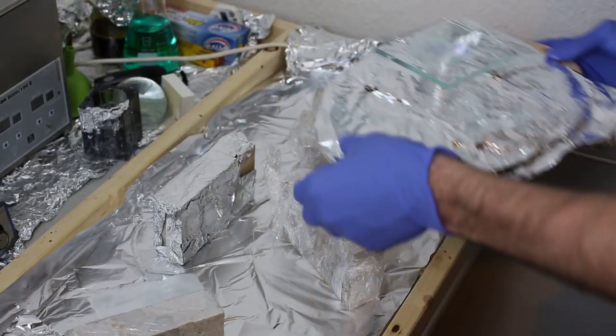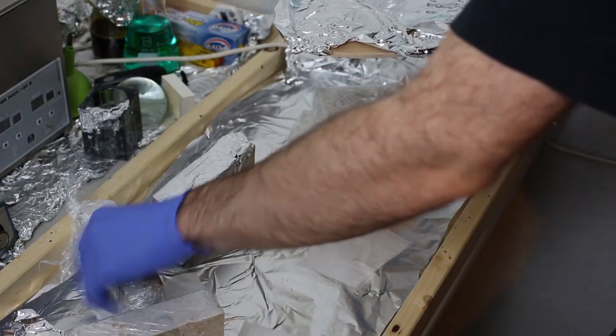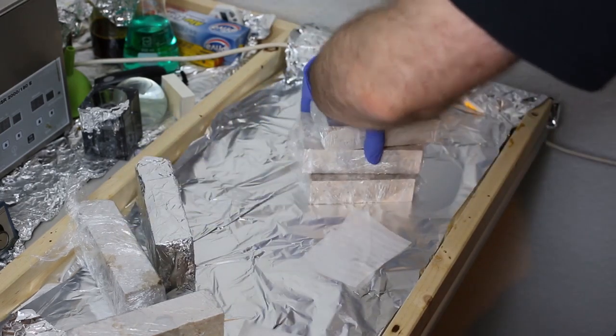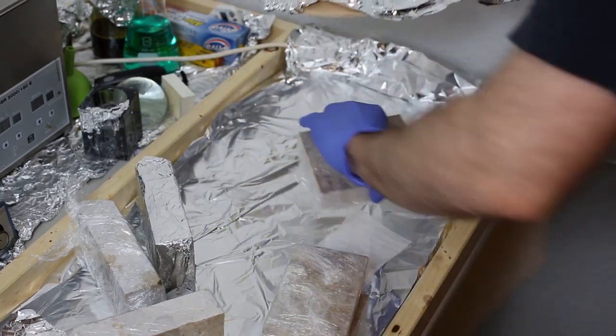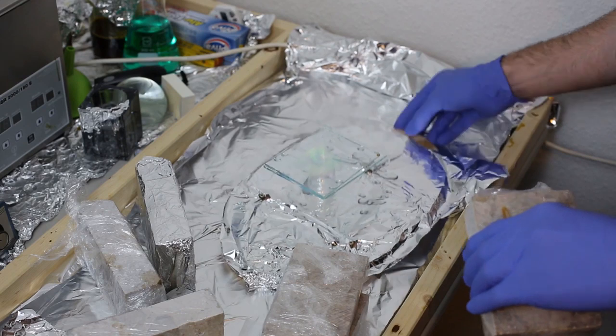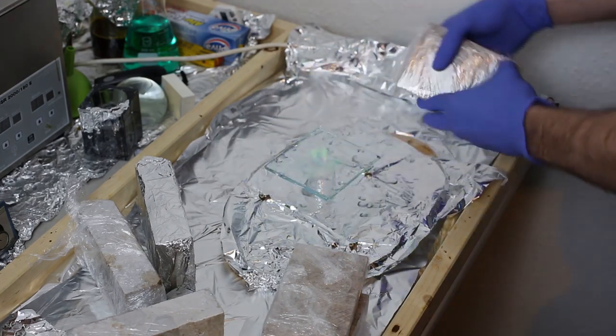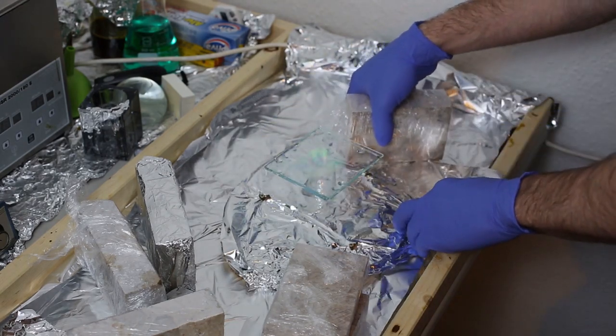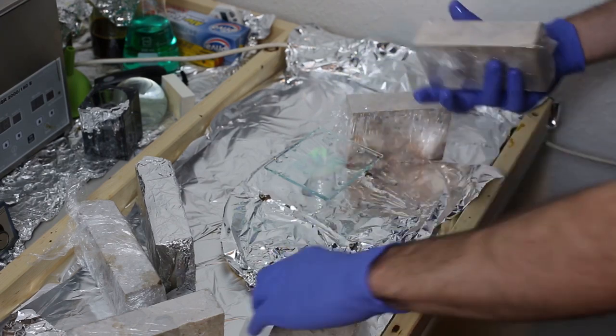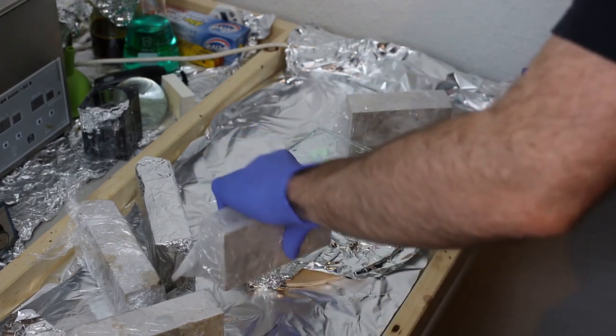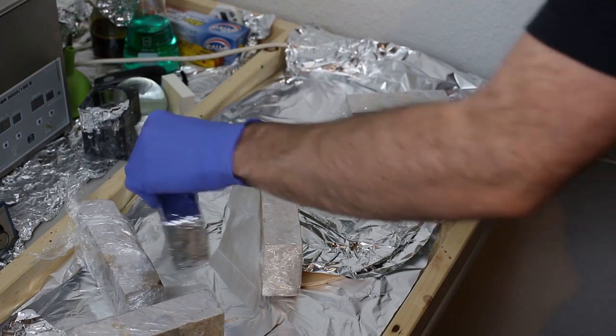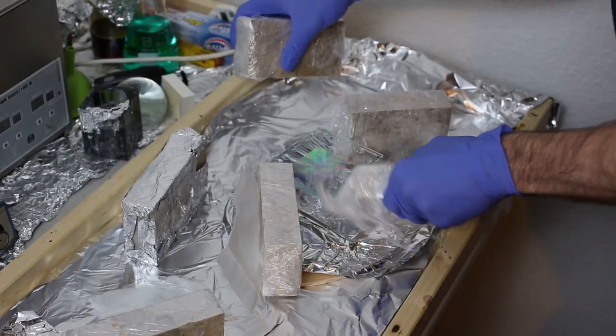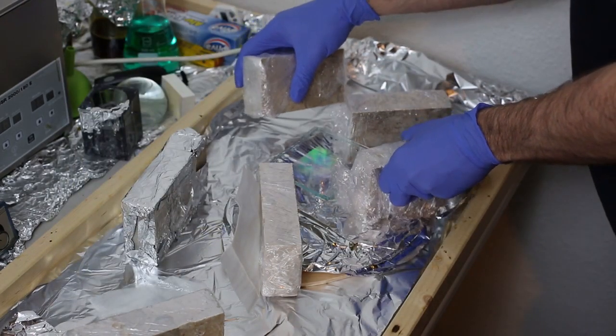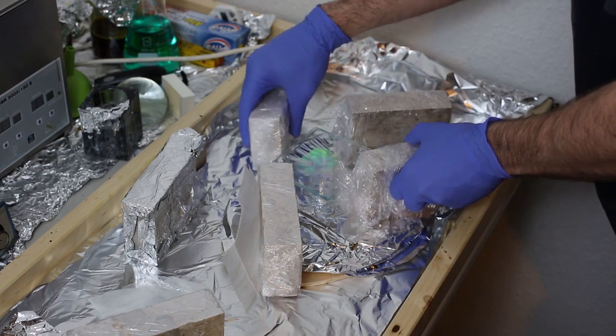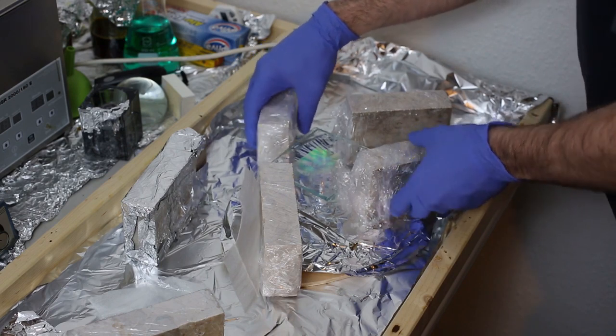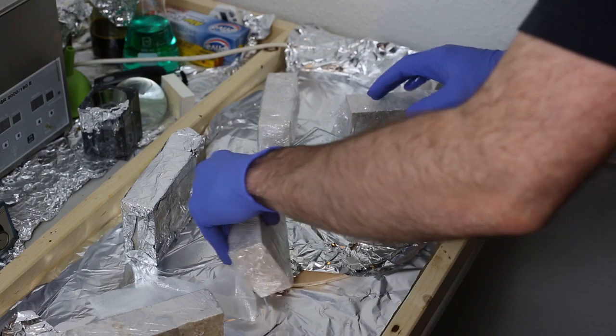Next, I bring the glass sandwich to a different area where I let it cure. I put 4 cinder blocks wrapped in saran wrap around the sealed hologram. I want the least surface area from the blocks to touch the soft glue, so I only make them touch with the corners. The cinder blocks will prevent the cover plate from sliding off, and because they touch the plate only with the corners, I will be able to remove them easily once the glue has hardened.